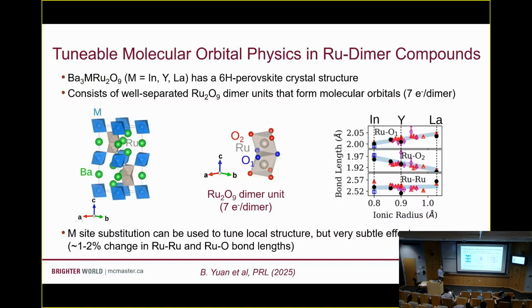And like the double perovskite crystal structure, this is a very tunable crystal structure. Okay, there's a bunch of different elements that we can put on this M site here, and that can continuously tune the crystal structure, although the changes are quite small. Okay? So we're going to focus on 3 particular compounds with indium, yttrium, and lanthanum. And you can see as we move across here from one element to the other, the changes in the key bond lengths here, whether that's ruthenium-ruthenium or ruthenium oxide inside these little octahedra, these are pretty small changes. So at the most, about 1 to 2%.